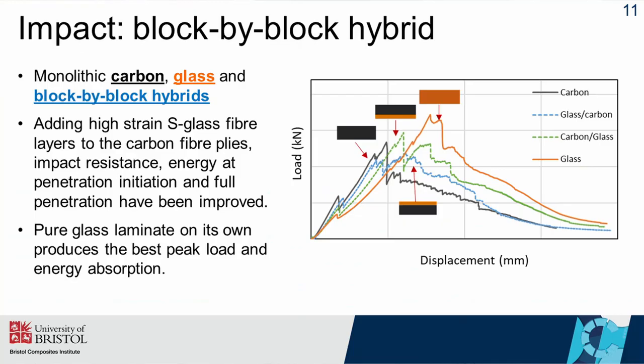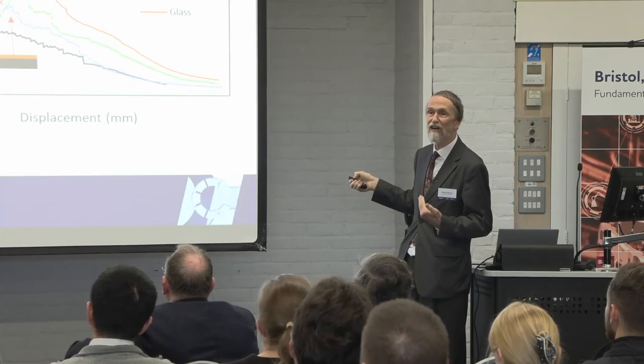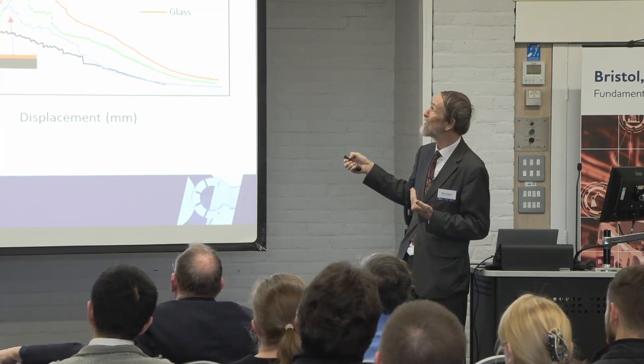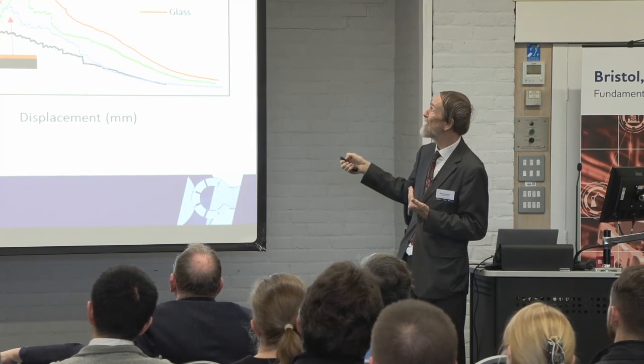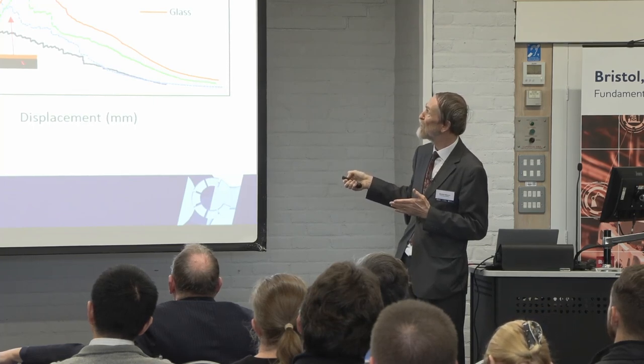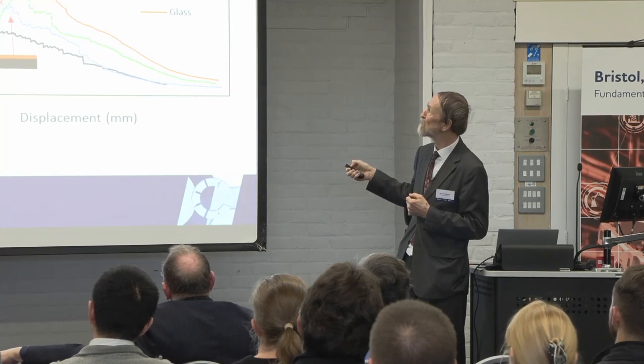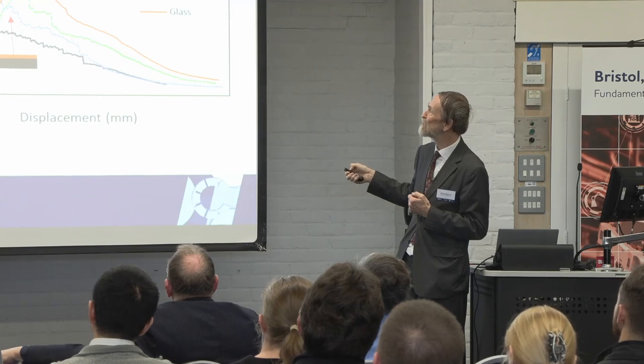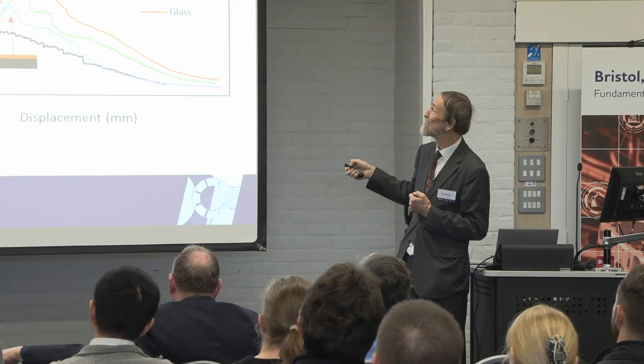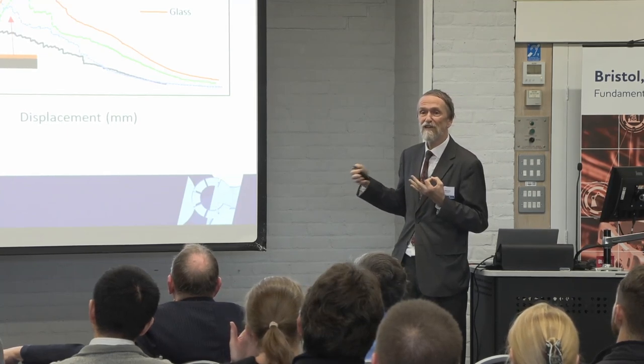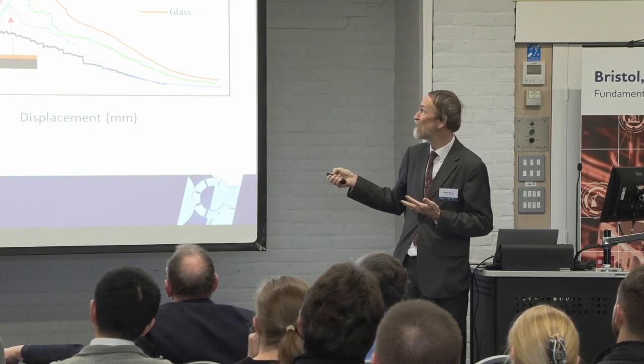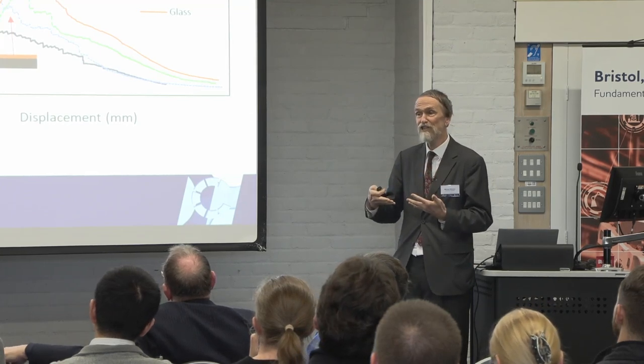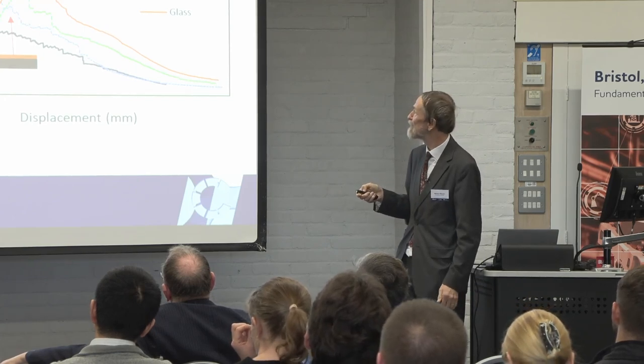This shows some work where Shun tested some specimens which were all carbon, which are the black ones, all glass or hybrid composites. The carbon is stiff, as you'd expect, but the actual energy under there is not so good. By introducing the glass, we see an improvement in the response. In fact, in this case, the all glass gives the best response. The all glass gives us both the highest load and the largest energy underneath that curve. But it's interesting, if you compare these two cases, they're both improvements on the carbon, but when we have the glass on the compression side, it doesn't produce such a large improvement. When we have the glass on the tension side, we get a much better improvement. That's really to do with the fact that a lot of the energy comes from the bending and the tensile deformation on the back face. It's better to have the high elongation material on the back compared with the front of the material.